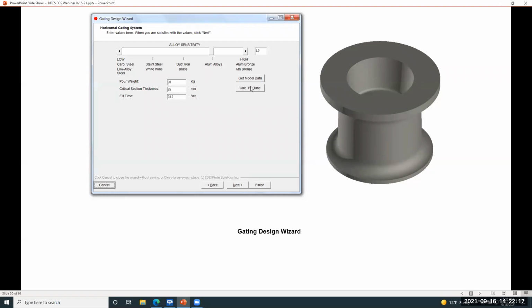When we enter that data, the system will calculate an appropriate filling time for us based on the overall weight poured and that critical section thickness. We can make adjustments to that filling time if we wish, but once we enter a filling time here, the rest of the gating system will be calculated in order to meet that filling time. So the sprue, the runner, and the gates are all sized so that we can meet that filling time.